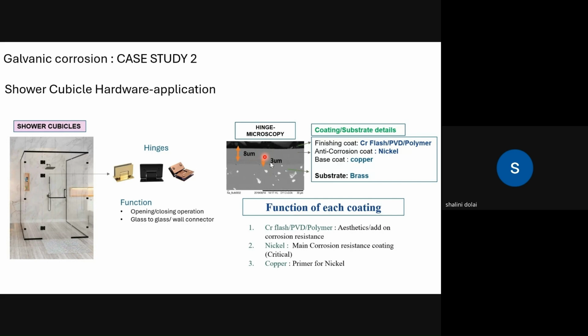Now this was showing pitting corrosion. You can see in your washrooms as well, if you have these kind of hinges, small black dots will be there. Now how to prevent it? Should I change my brass substrate itself, or should I increase copper thickness? Should I increase nickel thickness, or should I do something with the chromium? The game is to improve the life of the product with the least expenses.